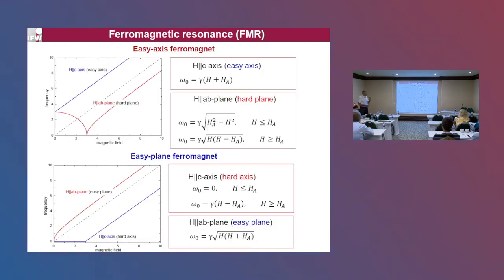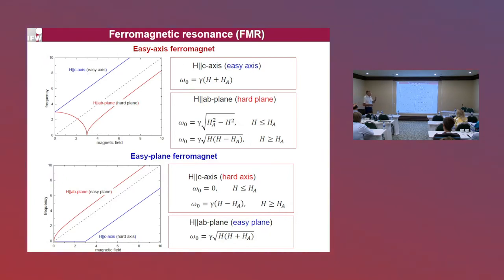In the case of ferromagnetic resonance, which is the subject of today's presentation: in a single-sublattice ferromagnet, one can excite two ESR modes by ESR. They are degenerate at zero magnetic field but acquire finite energy in the case of easy-axis anisotropy, where the magnetization prefers to stay out of the plane. If the field is applied normal to the plane, one mode develops linearly with magnetic field; the other mode first softens and then also develops linearly. This is distinct from the paramagnetic resonance branch.